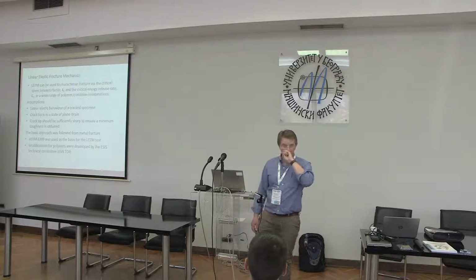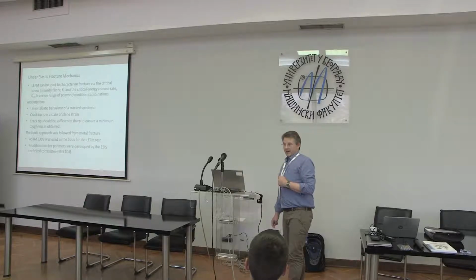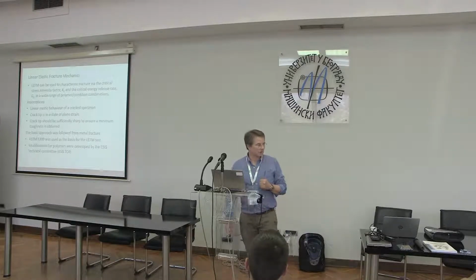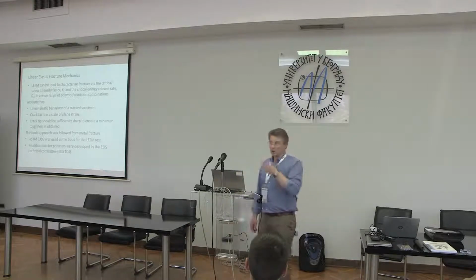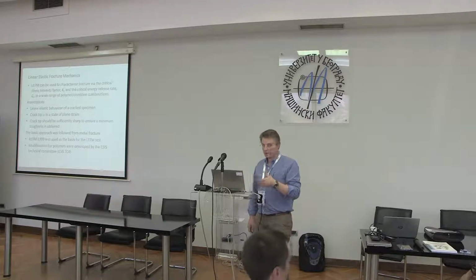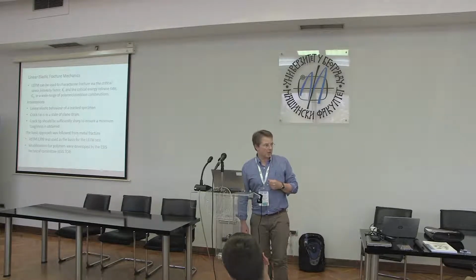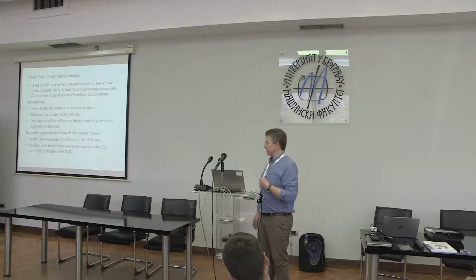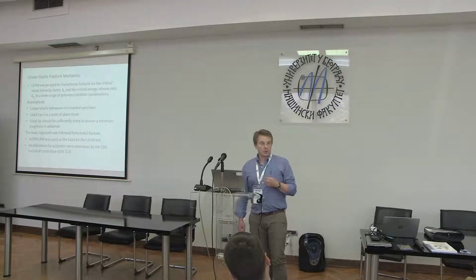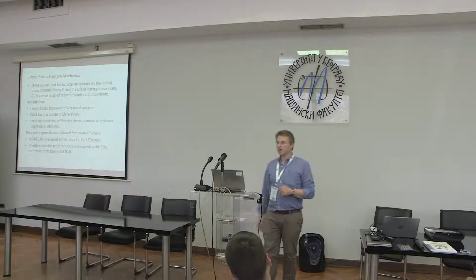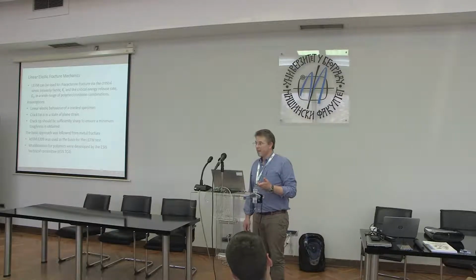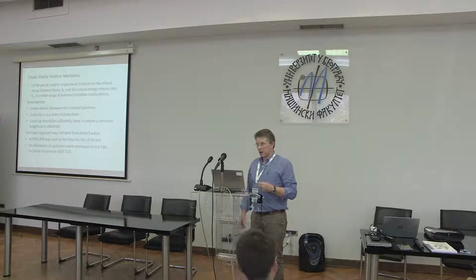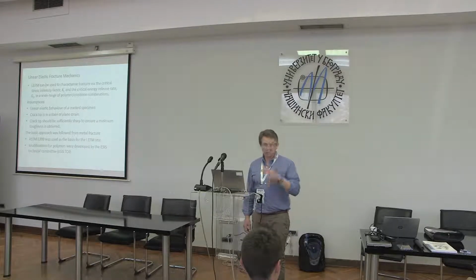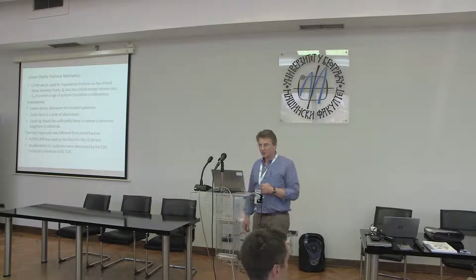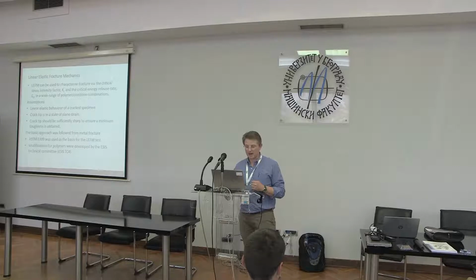Okay, so this is a point that we've debated at very great lengths, and it gets a little bit philosophical at times, because there is an argument that if you just keep making a crack sharper and sharper, you get a lower and lower toughness. But of course that has a major implication for the use of fracture mechanics. So the basic idea is that there should be some sharpness where if you make it any sharper, you don't get any lower value of fracture resistance. So there is some value there that we always try to obtain in our fracture testing, where we say we have a full state of plane strain, and our crack is giving us this lower bound value that we can go away and use in confidence. Okay. Now, as I say, it's slightly controversial, but we do hold by that principle.